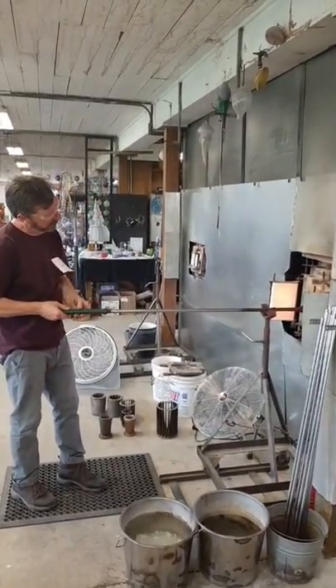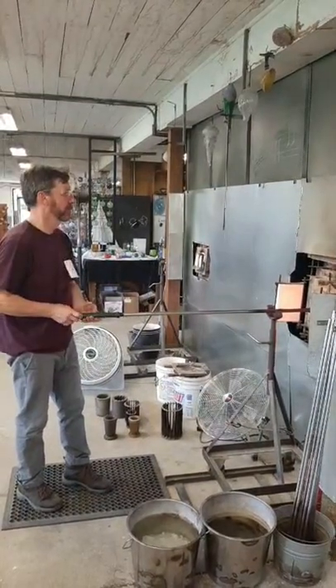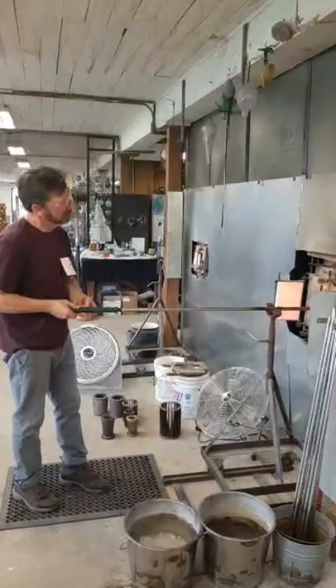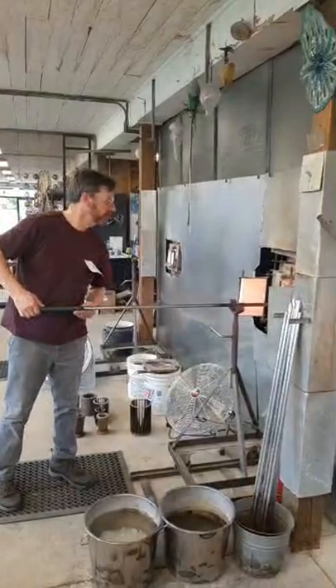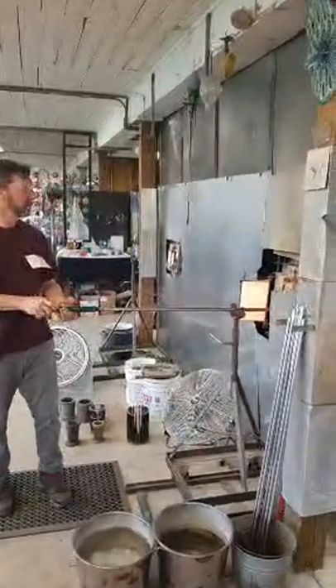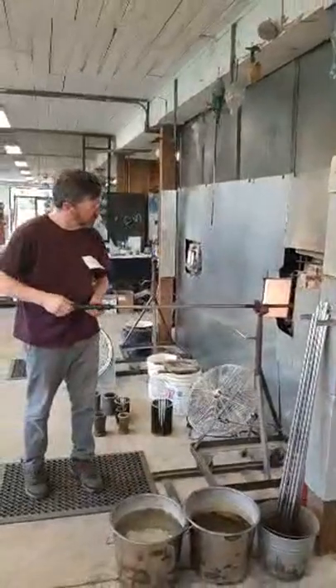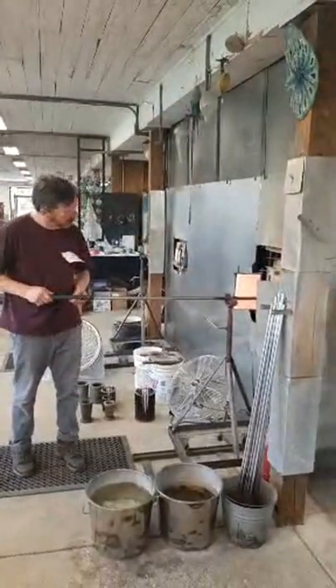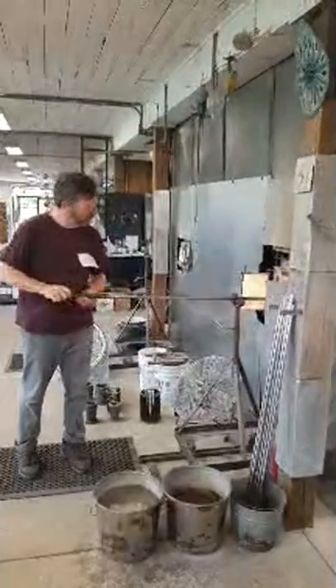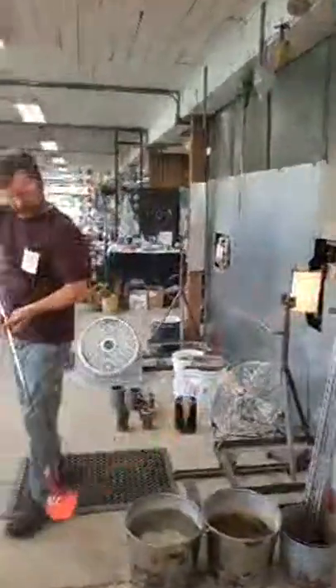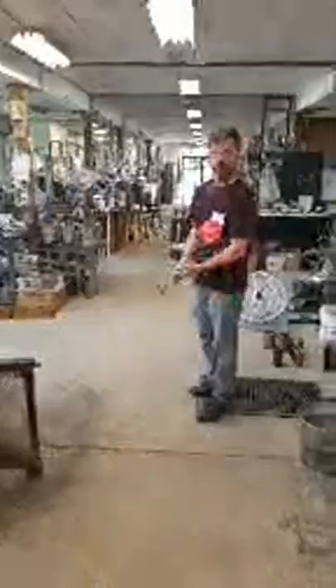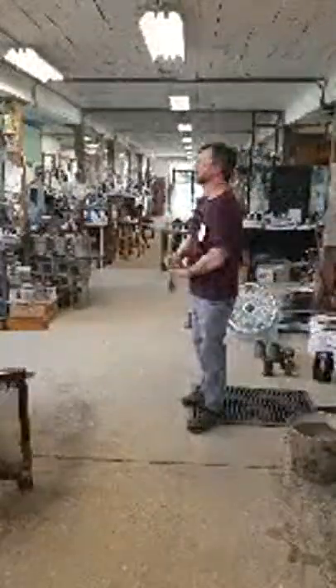And if that diameter is too large, you have a very much larger surface of the glass in motion, and it can crack and run down the side of the piece. So by constricting the neckline like that, you restrict the available space to move, and the glass doesn't spring apart. It's not much, but it's enough that if you don't have a good jack line cut, you're going to be in trouble.